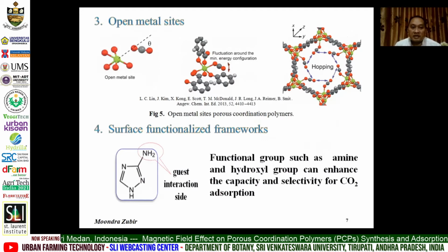The third type is the open metal site PCPs. These open metal sites can enhance gas adsorption after the metal ion opens the metal site of the PCPs. The fourth type is the surface functionalized framework. It contains gas interaction sites as functional groups, such as amine or hydroxyl groups. It can enhance the capacity and the selectivity for gas adsorption, especially for carbon dioxide. The interaction between the functional group and carbon dioxide gas enhances the selectivity and absorptivity of carbon dioxide.